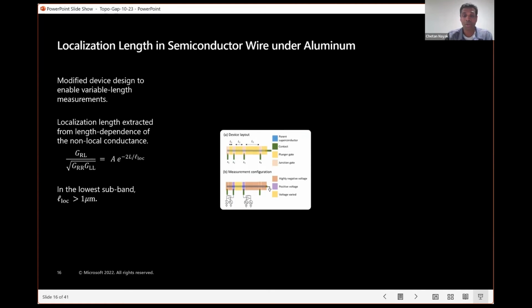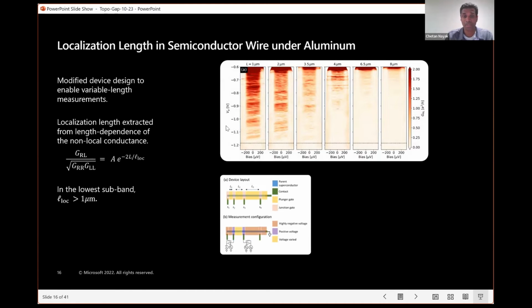And what we see is that here's a map of the non-local conductance as a function of bias voltage for different plunger gate voltages, which means different densities in the wire, for different lengths. So that's for different pairs. This is lead 1 to lead 2, 2 to 3, 1 to 3, and so on, all the way up to the 1 to 4 from here to here, which is the longest one. And across these different lengths, you can see how it decays exponentially, but there is signal even at 8 microns.